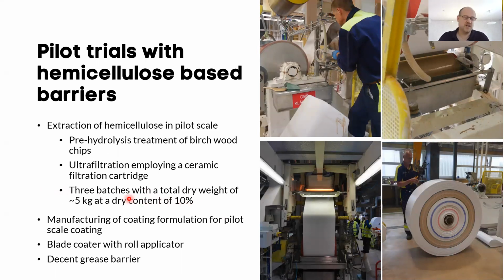We actually had a coating manufacturer who helped us to build up a coating formulation, and then also manufactured about 50 liters of coating color with this. This contained fillers and plasticizers and other things too, of course. But we ended up with that and went to get some paperboard and made some coating trials in the pilot coater at relevant industrial conditions. These are actually pictures from these trials.